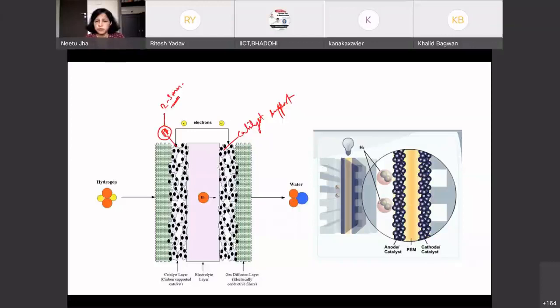So what are the advantages of this? First, it avoids platinum agglomeration, right? We do not want a lot of platinum to agglomerate with each other. So platinum agglomeration can be avoided. And that is why you need a catalyst support which is stable, because if the material is not stable, it will dissolve slowly with time and platinum particles will agglomerate.